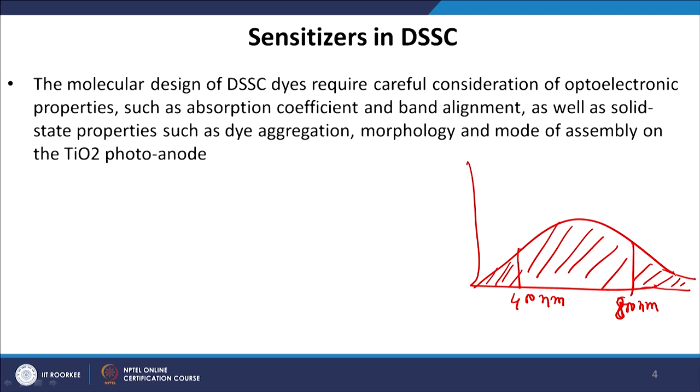The next consideration is morphology — how is the dye molecule distributed over the surface? The TiO2 photoanode is sintered at 450°C to make a mesoporous structure, with the objective of absorbing as many dye molecules as possible. Ideally the dye should penetrate beyond the surface. If dye is only adsorbed as a monolayer on the surface, the amount of charge carriers generated by photon absorption is not as high. In the ideal case, dye should also penetrate into the bulk of the material, so its distribution over the n-type semiconductor plays an important role.